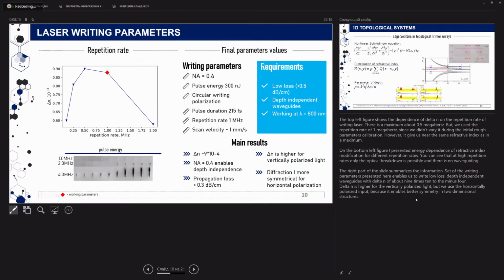The top left figure shows the dependence of delta n on the repetition rate of the writing laser. There is a maximum about 0.5 megahertz, but we use a repetition rate of 1 megahertz since we didn't vary it during the initial parameters calibration. However, it gives us nearly the same refractive index as in the maximum.